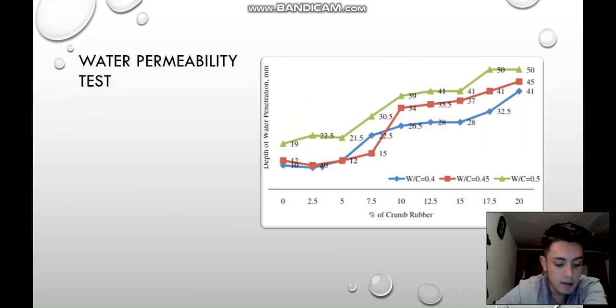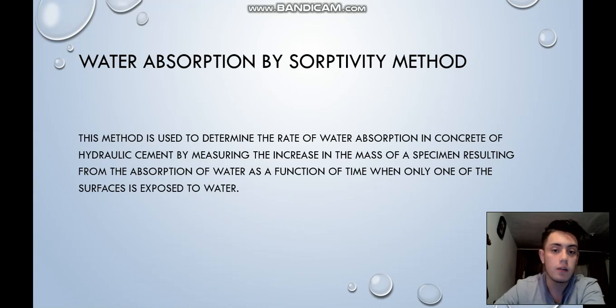Water permeability test. In this table you can see the depth of water penetration in millimeters against the percentage of tire dust. It can be deduced that the greater the amount of tire dust, the greater the depth of water penetration, where it can be noted that the water cement ratio of 0.5 is the one that allows more water passage through the material, followed by 0.45 and 0.4. For the absorption sorptivity method: the method is used to determine the rate of water absorption in concrete of hydraulic cement, by measuring the increase in the mass of specimens resulting from the absorption of water as a function of time when only one of the surfaces is exposed to the water.